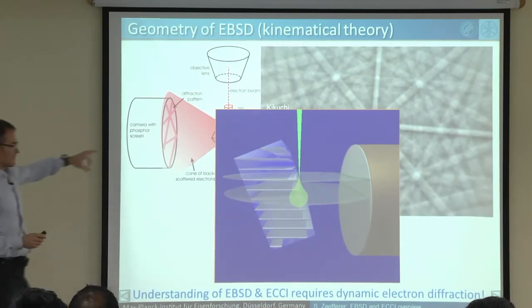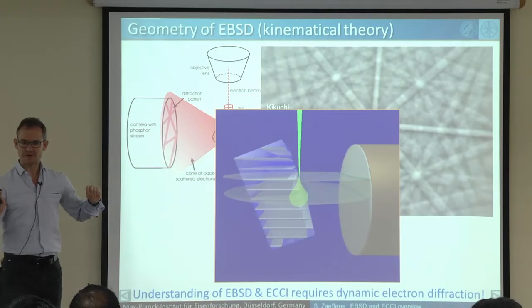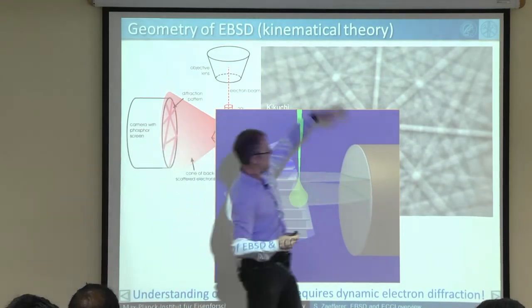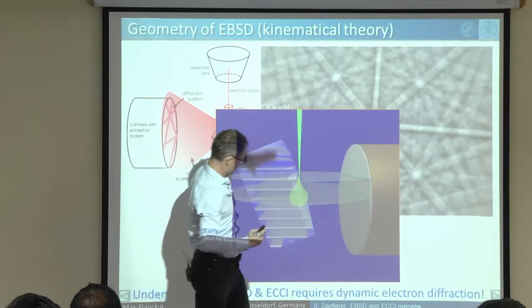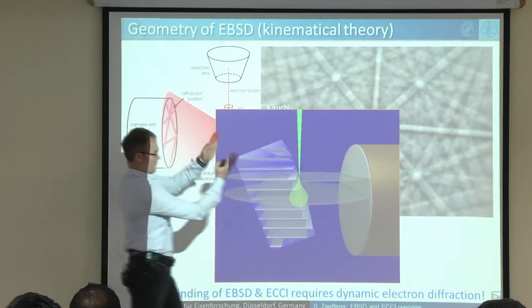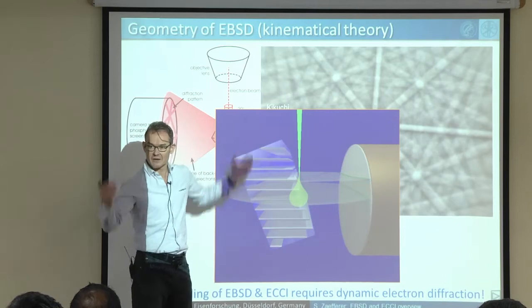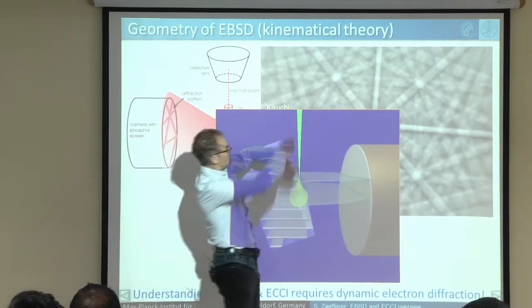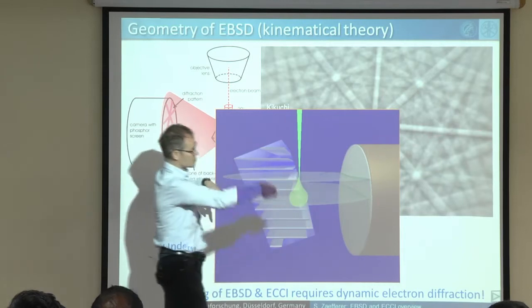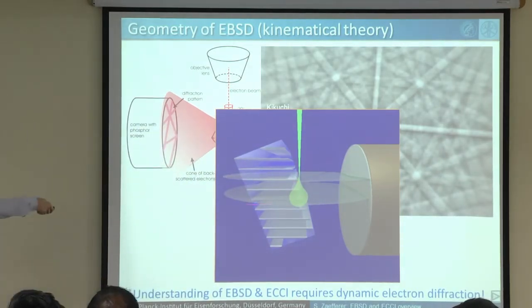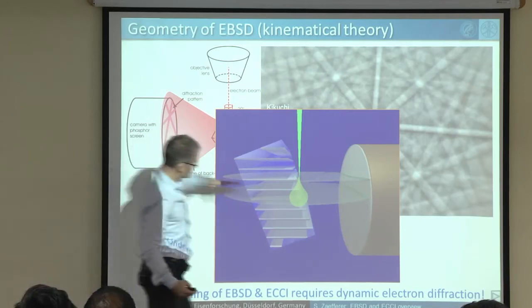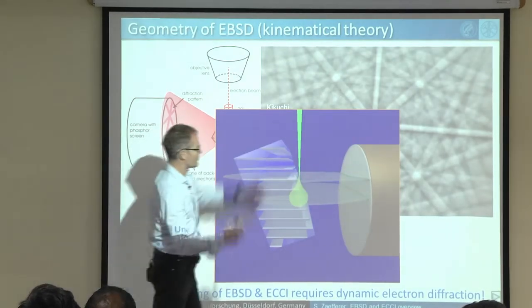So the geometry is very, very simple of EBSD. In principle, each of these bands is just a projection of the lattice planes onto the phosphor screen. And as we have many different lattice planes in a crystal, infinitely many in principle, we get all this set of projections, these gnomonic projections of these lattice planes. And the Bragg angle is actually just the opening angle from one line to the other line here. So that's the Bragg angle. That's where Bragg plays a role, and the rest is just pure geometry. Just take the planes, project them onto the screen, and there you are.